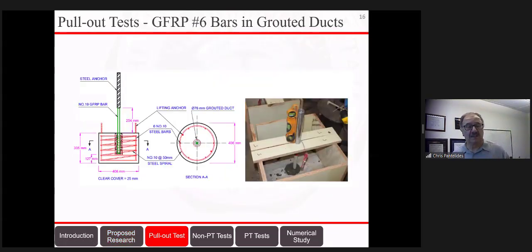So before we started building these 4 specimens, we realized there was no information on what is the pull-out capacity of a 19 millimeter or number 6 bar in a grouted duct. So we constructed some specimens for pull-out testing, so we could make sure that when we embed them inside the grout, we will actually have a good performance.